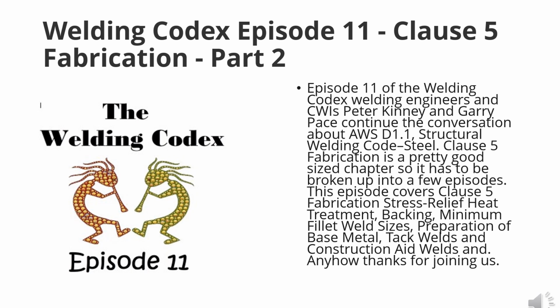But what I'll also say about this is, if you're in the qualification area, what I have always tried to do was use the same tacking process during my qual as I want to use in production. And I usually put a macro there so if someone ever says, hey, how do you know it's consumed? I have a little picture to show them that there was supposed to be a tack weld there and there's no difference in the weld metal. That's associated with qualification and not fabrication, a little lesson learned I got there.